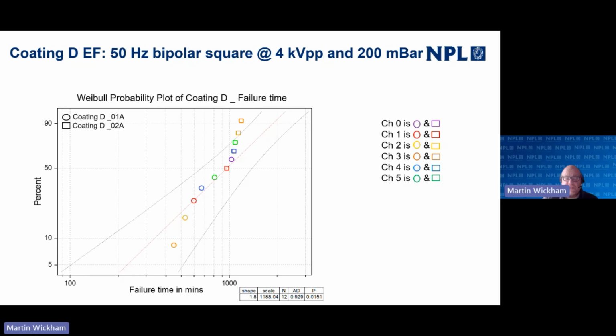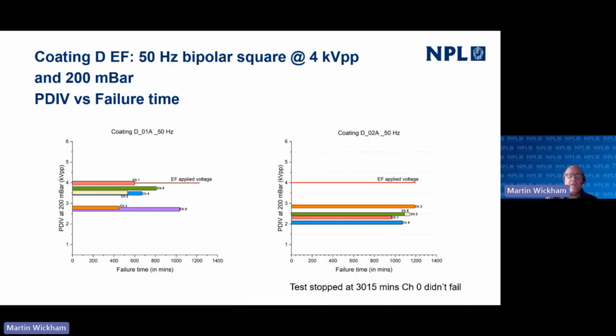We're honest, we don't know why these two samples appear differently. We dry the samples out before we start. We try and keep everything as close together as possible, but that'll be an issue that we're looking to gain more information on as we go forward in this project. Most of these samples were below the electrical fatigue applied voltage, so you can see they're failing, and you can definitely see from the lengths of the bars here that the second sample lasted longer than the first sample, even though the inception voltages were generally lower with the second sample than the first sample.